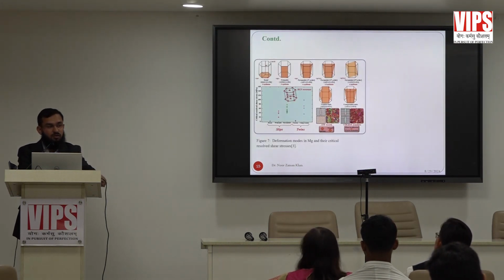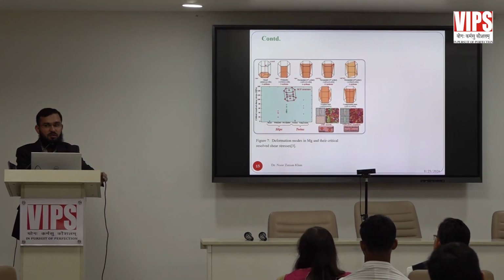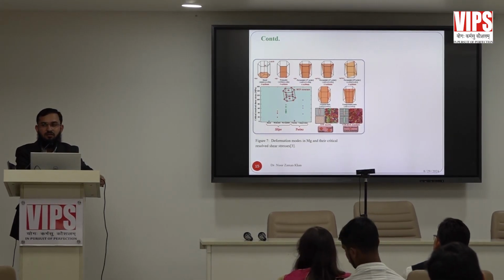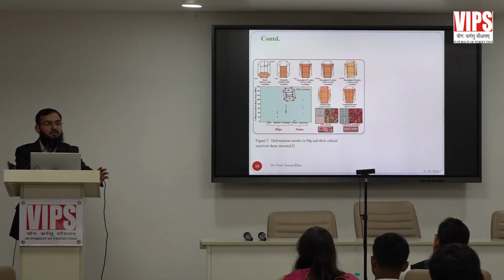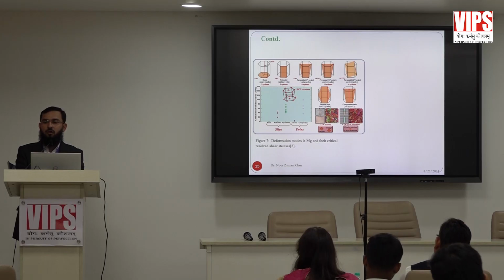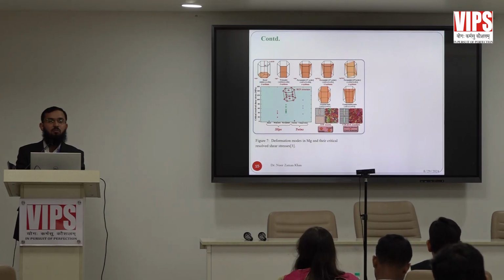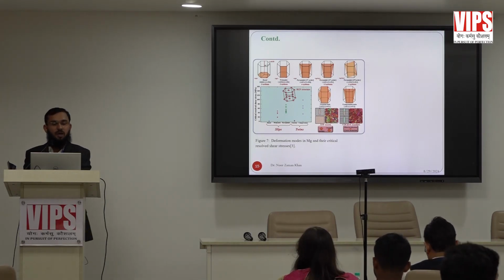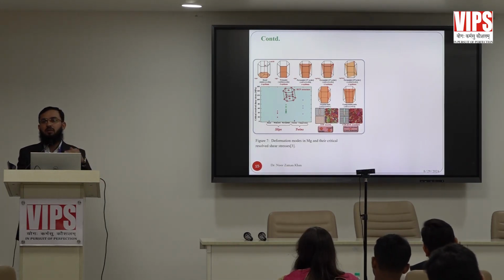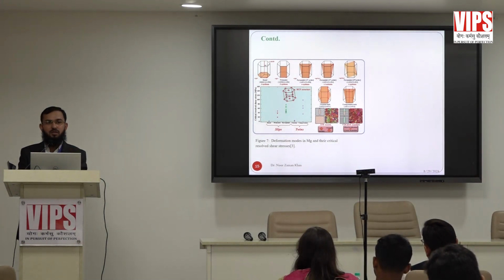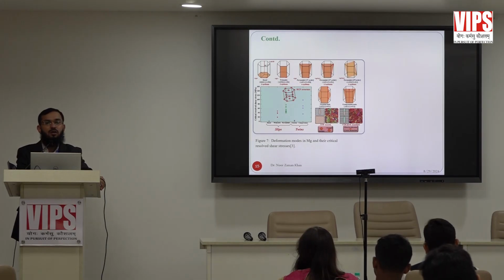I should not discuss the technical content of material science in detail. This is nothing but the slip system of magnesium alloys. Very briefly, if you want to deform any material, there are some slip systems. In magnesium, there are three different planes: basal plane, prismatic plane, and pyramidal plane. If you want to deform magnesium, the basal plane slip system is active at room temperature, but the other two slip systems are not active at room temperature.